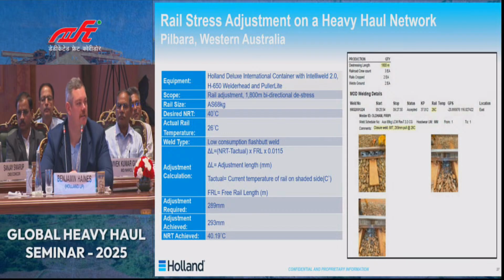The desired NRT for this particular network was 40 degrees. The actual rail temperature at the time was 26 degrees Celsius. The weld type we used was a low consumption flash butt weld. The adjustment calculation used for this network is: adjustment length equals the NRT minus the actual, times the free rail length, times the coefficient used by that network, being 0.0115. The adjustment required was 289 millimetres, and the adjustment achieved on this day was 293 millimetres.